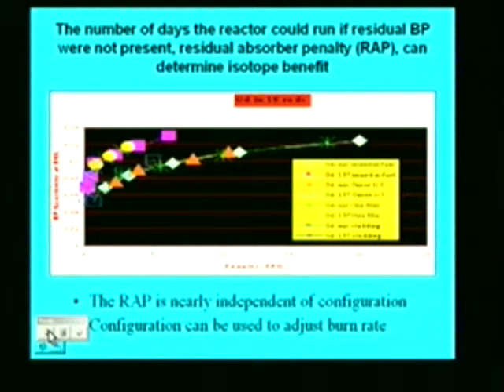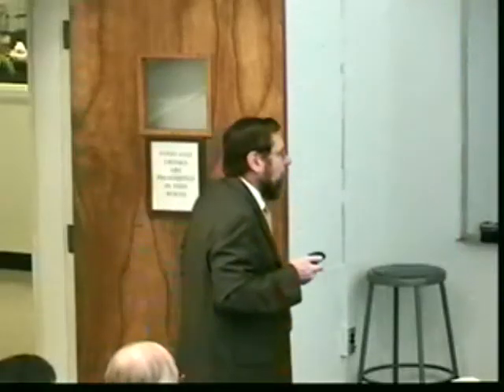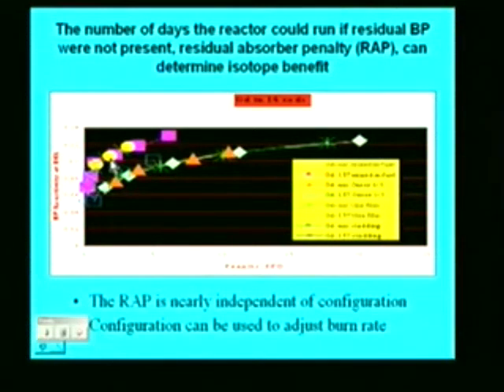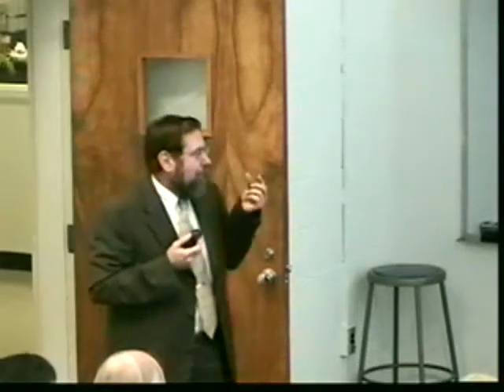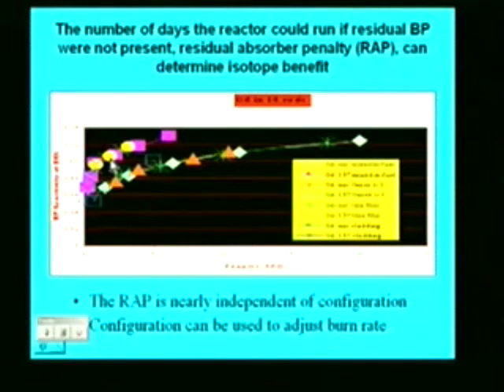And what I'm plotting here is the reactivity due to burnable poison as a function of a penalty. The number of days that a reactor could be run if the residual burnable poison were not present, we'll call the residual absorber penalty, the RAP. And this can be used as a parameter to determine the benefit of our isotope separation. If you work out your model with the burnable poison and determine how many days it will last before K effective drops below 1, then you take the burnable poison out and run the same thing and see how many days it takes to drop subcritical. And the difference in that is the penalty that you paid by having that burnable poison in there.